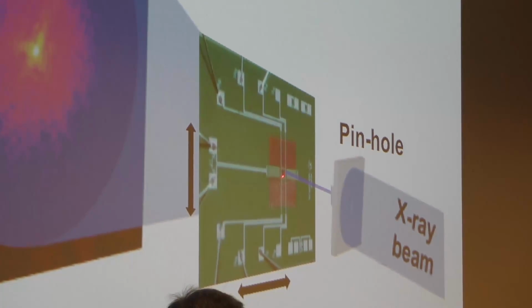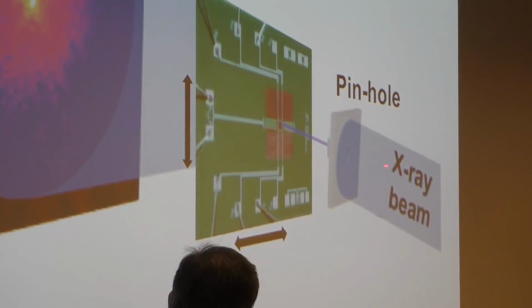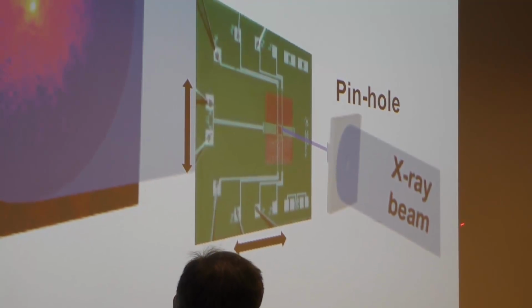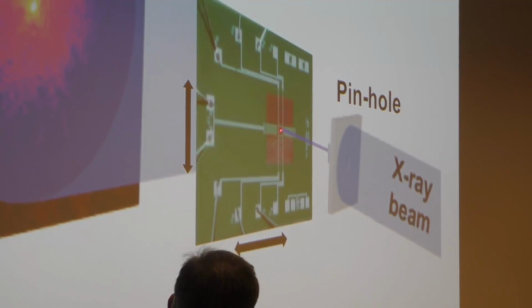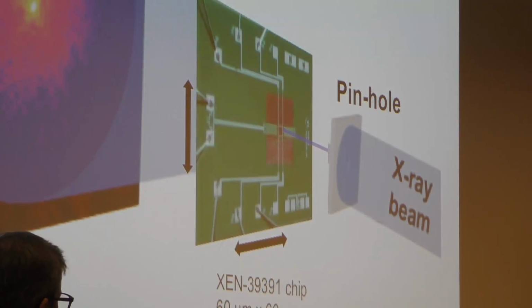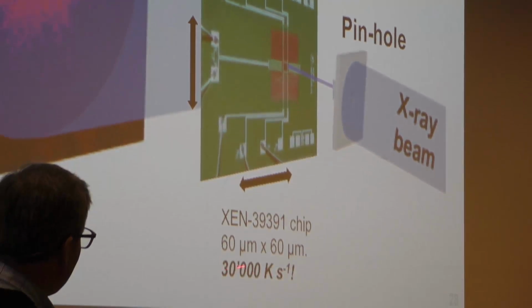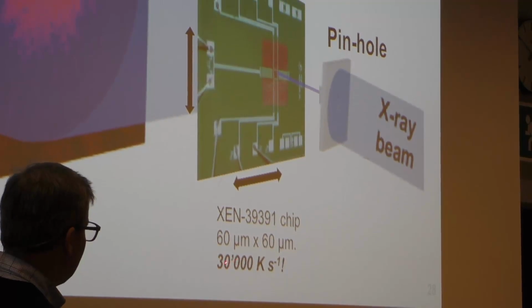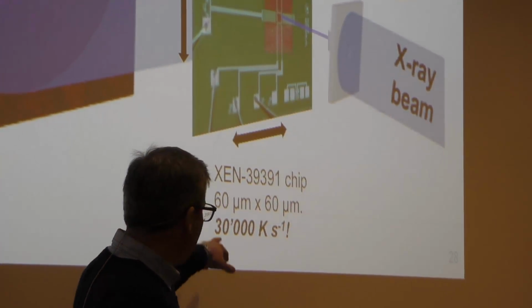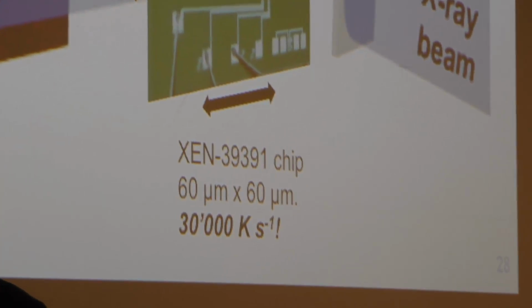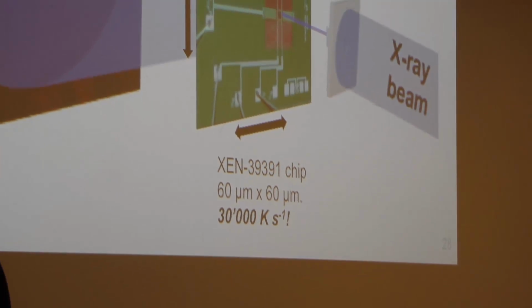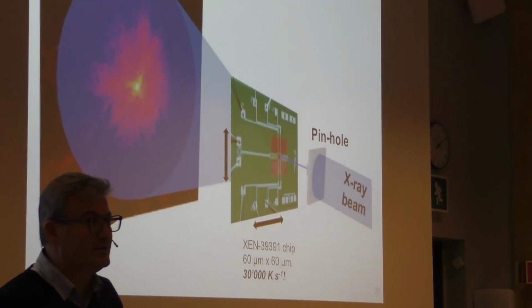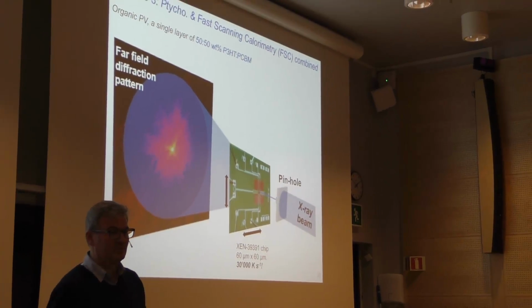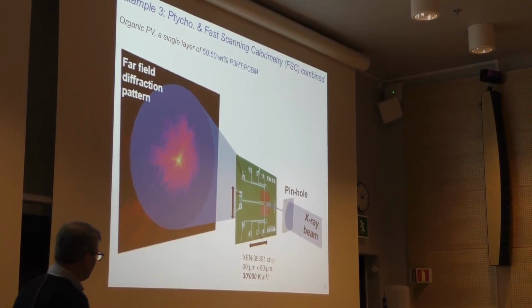Here we have a small silicon nitride window, which is transparent to X-rays, which means that when we are sending the X-rays towards this area, we can look at the diffraction pattern on the backside and again see what is taking place here. And what is fantastic about these fast scanning calorimetry chips is that people using them claim that they can have temperature changes of 30,000 Kelvin per second, and this is owing to the very low thermal mass that you have in these cases, right? It's just a very, very small sample, which can then be heated and cooled